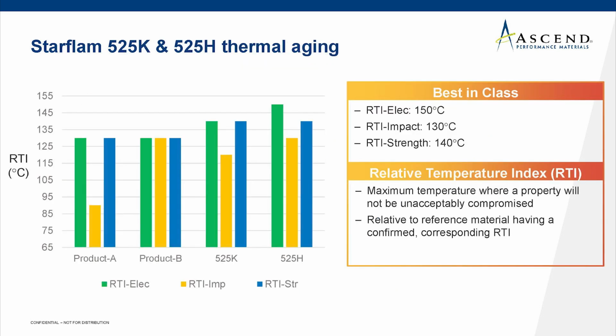One of the most important characteristics for electrical connectors is that we have good thermal aging performance. And this is showing how both our K and H heat stabilizer grades compare to competitor products. Relative temperature index is a reflection of the maximum temperature where a property will not be unacceptably compromised. And this typically means that the point of failure is around 50% of the original, unaged value. It's also measured relative to a reference material, so one has to select a reference material carefully, and it will have already a confirmed corresponding RTI.